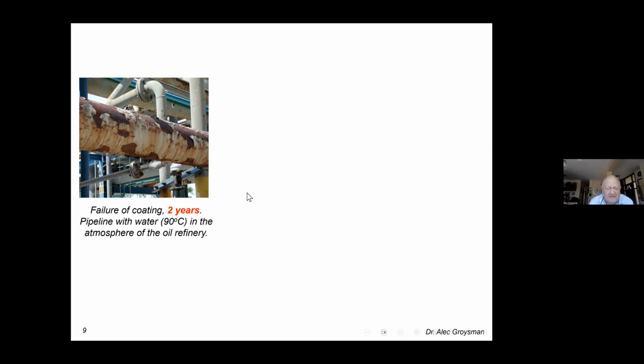The first event, failure of coating, as you see, during 2 years at an oil refinery. Pipeline with hot water, 90 degrees centigrade, in the atmosphere of the oil refinery, as you see, the coating failed. These heat releases, and it is important that people, staff, the workers and operators cannot go around this area.